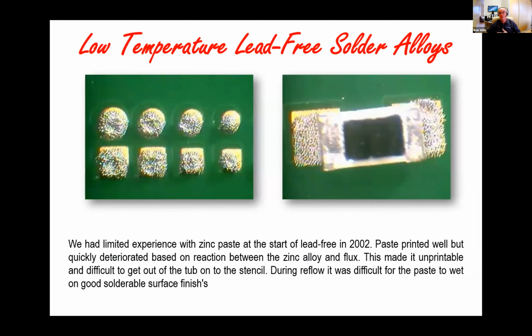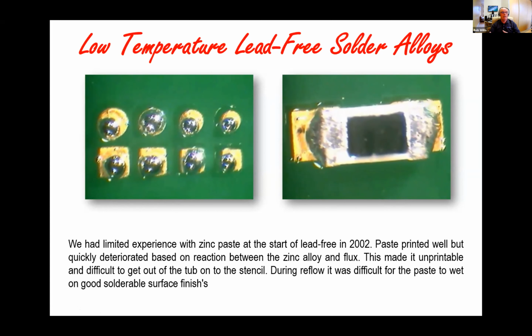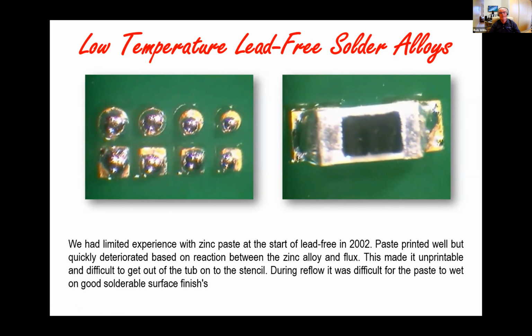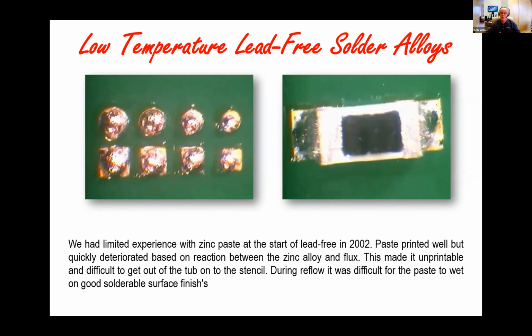If I go back to 2002, I messed around with tin zinc materials when I returned from Japan on some products. But one of the problems with these materials is wettability on surfaces, high oxidation rates within the paste itself. And as you can see in these two video clips, the wettability onto certain surfaces can be delayed. So these materials also were very difficult to print because they had a very short life expectancy. They went from beautiful solder paste to something more like cement, and then a solid cement after literally a couple of hours. So they weren't the ideal solution. But again, that's us learning about materials.